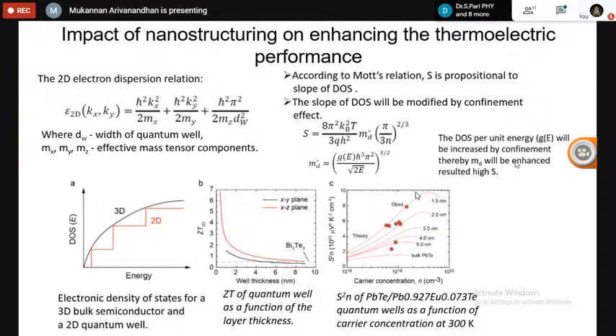Okay, and once if you have this kind of change in the density of states, that will lead to change the effective mass, since the effective mass is a function of density of states. Okay, so once if you increase the effective mass through the confinement, then the S can be improved, because S is directly proportional to the effective mass. The S is nothing but the Seebeck coefficient. So by doing this way, you can independently control the Seebeck coefficient and electrical conductivity.